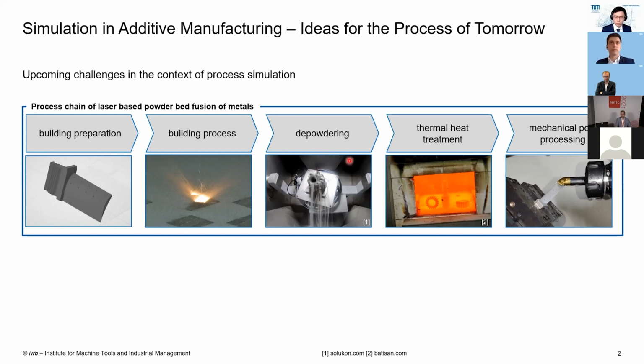next step, the depowdering. Here, the components are depowdered by an excitation with a frequency to remove even the smallest amounts of powder. And afterwards, we have the post-treatments and the post-processing steps, for example, here the thermal heat treatment, the stress relief annealing, for example, and also the mechanical post-processing to prepare functional surface areas.